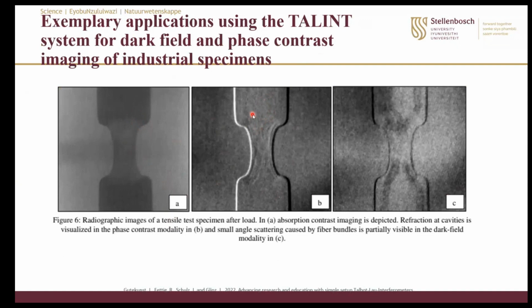However, what they then did is they broke and pulled out the fibers in the samples, and because phase contrast enables enhanced edge detection, they were able to see the parts where the fibers were pulled. Because this tensile sample is a carbon fiber sample, and carbon fibers increase X-ray scattering, that was seen on the dark field imaging, where the parts with no dark field signal, where we are not seeing the scattering, are the parts where the fibers were pulled out.